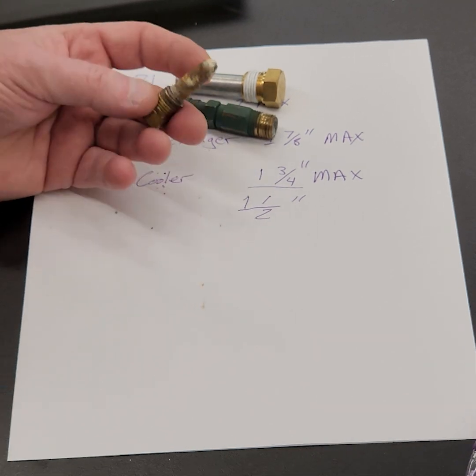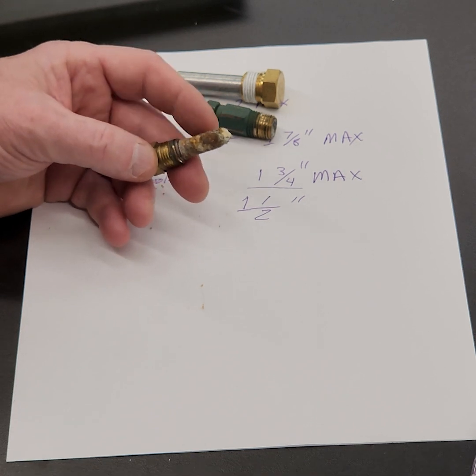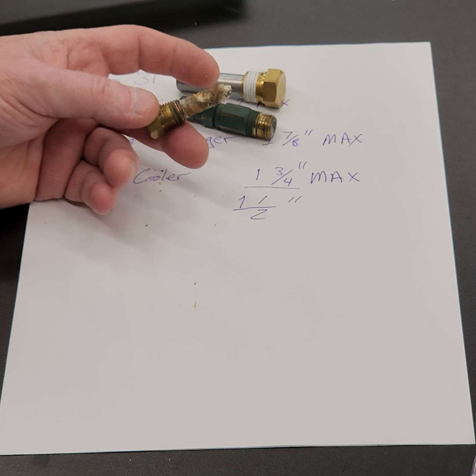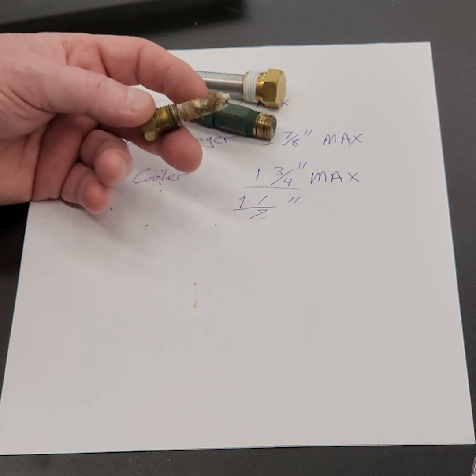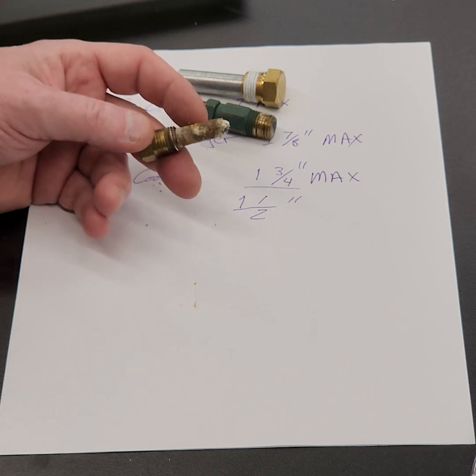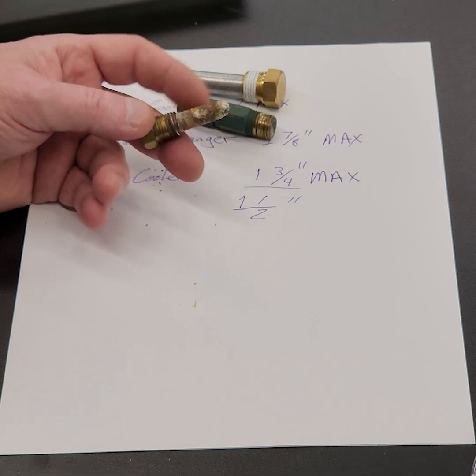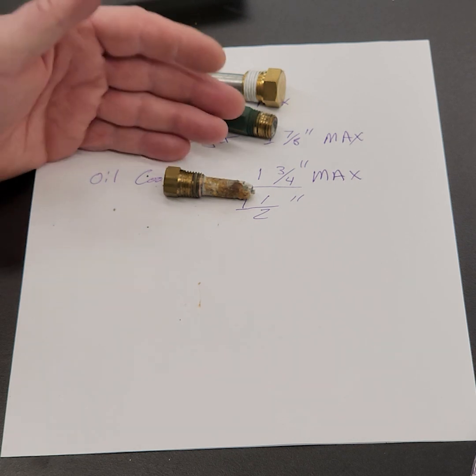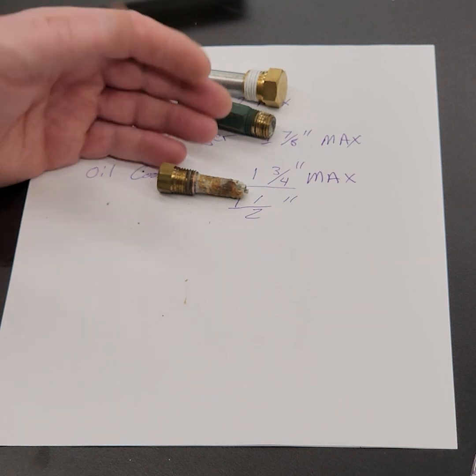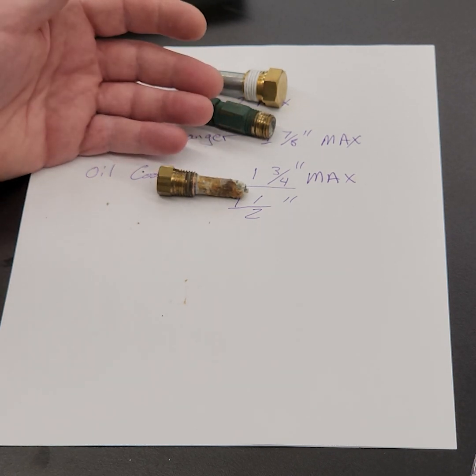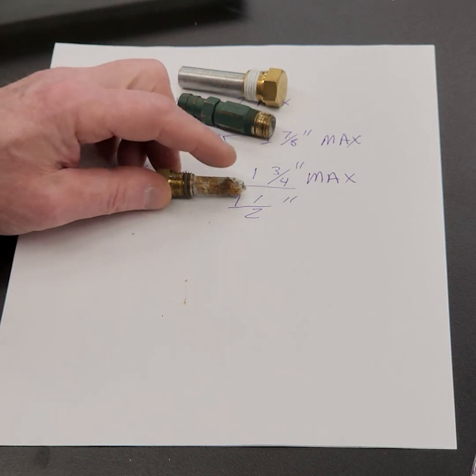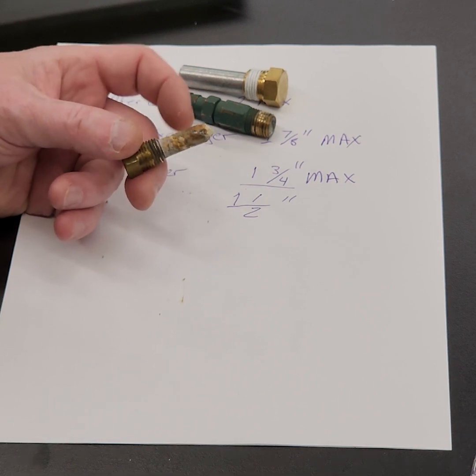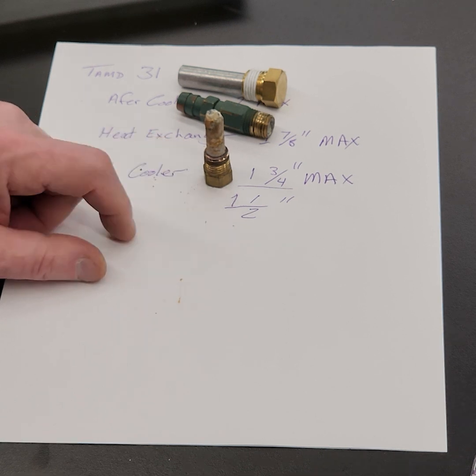So I would say, let's just use $20 a piece. Let's use today's numbers. Say these are $20 a piece, and you need to change them twice a year. That's 20, 40, 60 times two. That's $120 worth of anodes, probably a lot less than that. You can buy them online. But when you think about $120 a year versus an aftercooler tube assembly that's maybe $2,500, $1,500, it's cheap insurance over the years to do that. Heat exchangers and aftercoolers will last a long, long, long, long, long, long time with anodes in these. If the anodes fail, then the next thing that starts to corrode is the weak link of whatever that cooler is made of. Silver solder, tin, copper, copper nickel is very, very good. It's a very, very good product today that they use in those tubing bundles. That aftercooler is an aluminum housing. So if you don't have anodes in there, you still can have galvanic corrosion take place inside that housing.